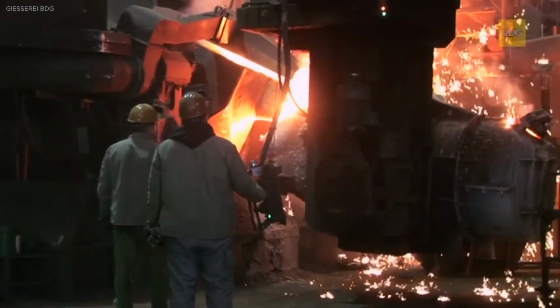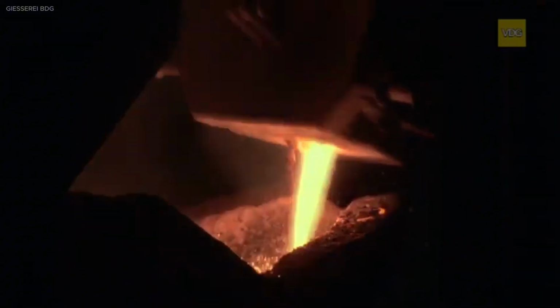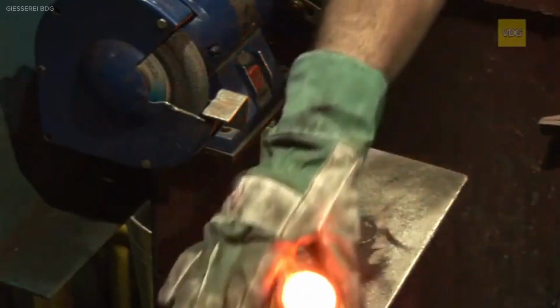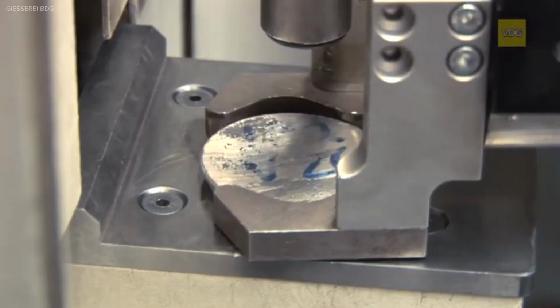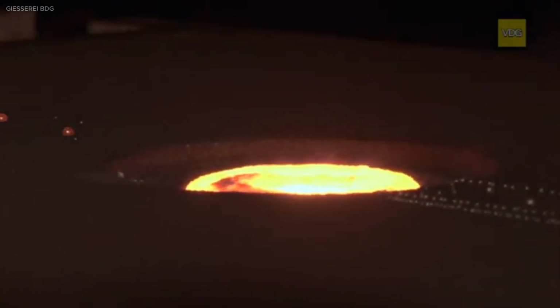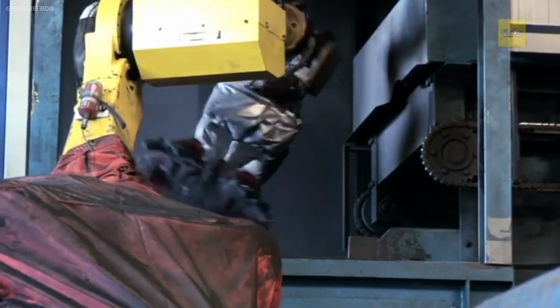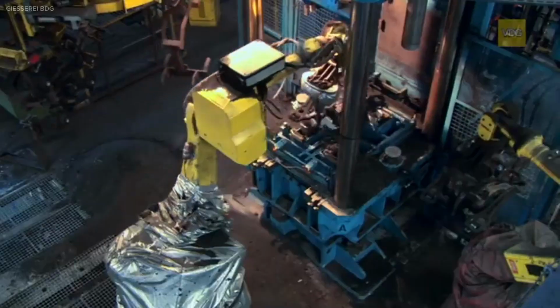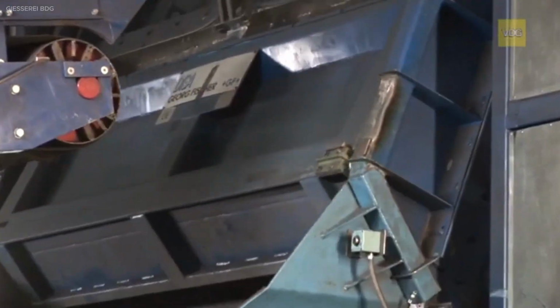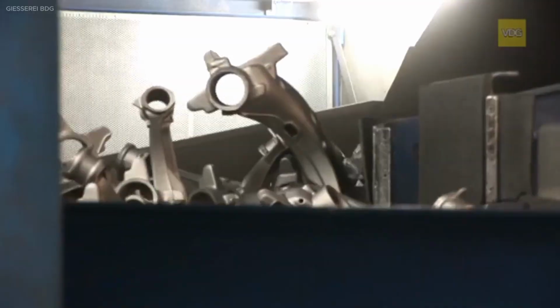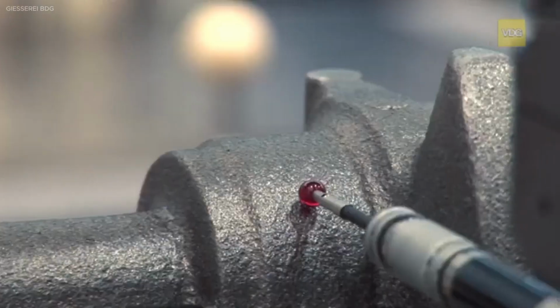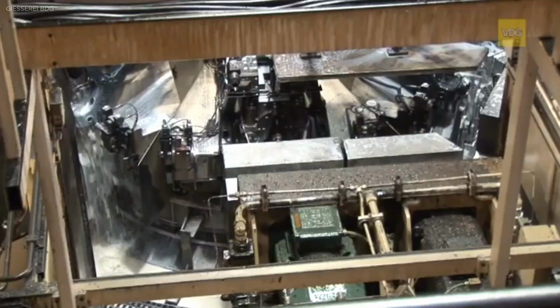The sand core is shaken out, and the gating system and risers are cut off. In the finishing shop, residual burrs are removed, and the casting is blasted with stainless steel shot to clean its surface. The sand is reprocessed, and metal scraps are remelted, reflecting the industry's commitment to sustainability. This process, scalable to large castings like wind turbine hubs or ship engine blocks, underscores casting's versatility.